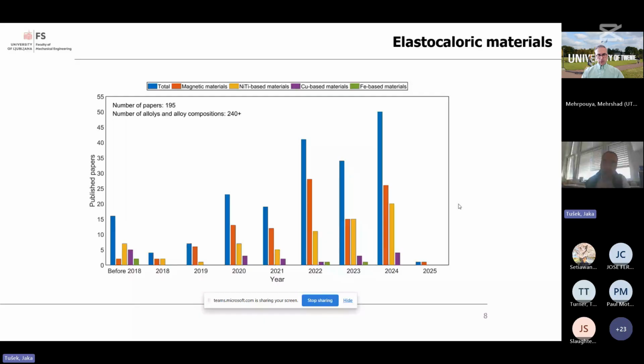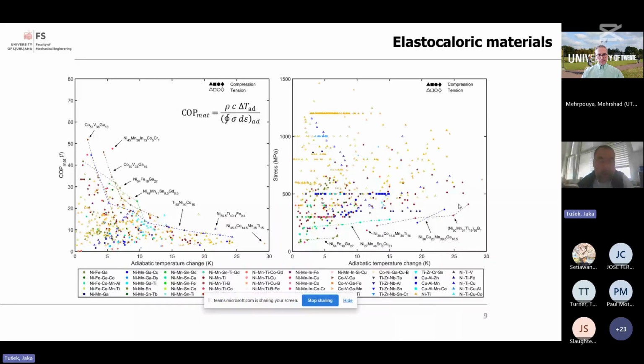We have recently performed an overview of practically all, to the best of our knowledge, elastocaloric materials published over the years. Those 2 plots show the material COP as a function of adiabatic temperature change, and also the stress required to reach these adiabatic temperature changes, again as a function of adiabatic temperature change. So we would like to be very efficient, so we would like to have COP of material as high as possible, and also large adiabatic temperature changes, so we would like to be here in this plot, but at the same time we would prefer having lower stress for the transformation. So in that end, we would like to be somewhere here. So let's talk a little bit more about the COP of a material.